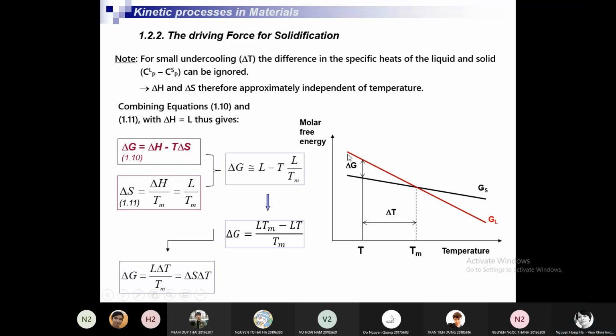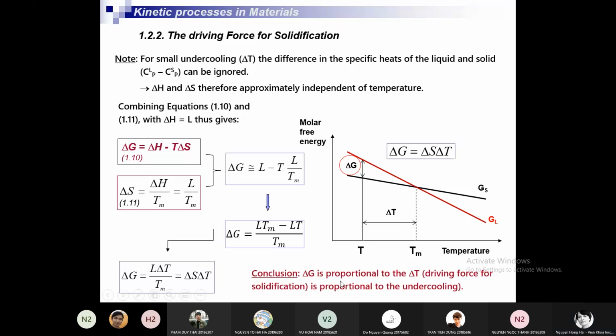Because this driving force for transformation or solidification is proportional to the undercooling. Very, very important conclusion. Delta G equal to delta S multiplied by delta T. Now, the conclusion. You should remember this conclusion. Delta G, the driving force for transformation, is proportional to delta T, to the undercooling.